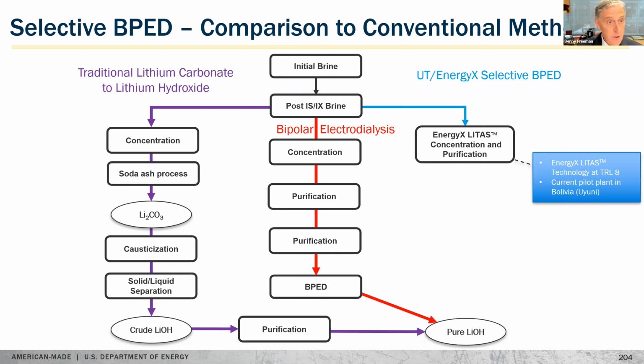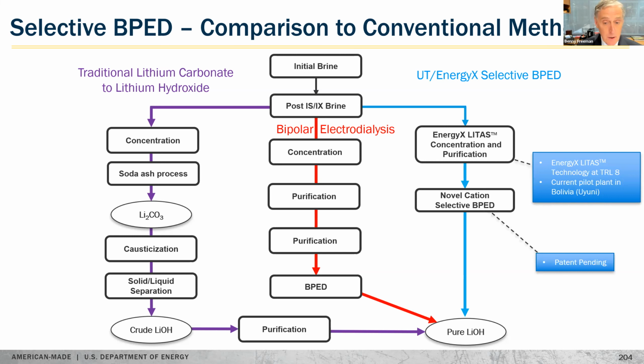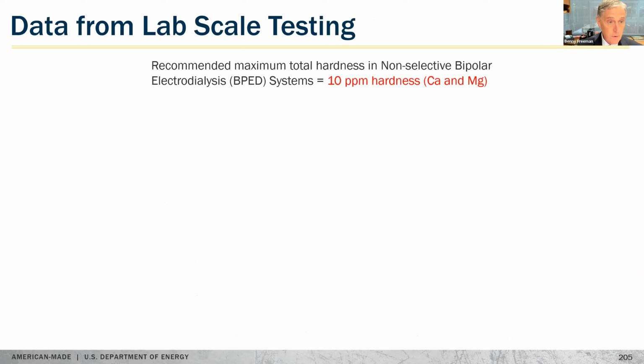The UT Austin EnergyX selective bipolar electrodialysis membranes takes that brine and first concentrates it in the EnergyX LITAS process that is currently being scaled at, in pilot tests in Bolivia, and combines it with our selective bipolar electrodialysis to make pure lithium hydroxide. Next slide. So this is a little bit of information that's coming from the lab.